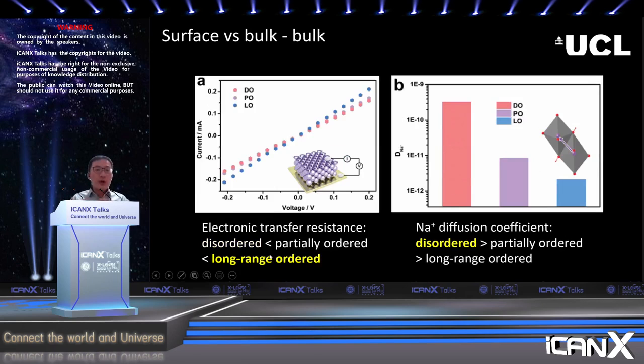What we did is we tested the electronic transfer resistance of the three samples, and we found the amorphous titanium dioxide shows the lowest electronic transfer resistance, and the sodium diffusion coefficient also has the highest value in the bulk structure of titanium dioxide in the case of amorphous structure, compared to the partially and completely crystalline structure.